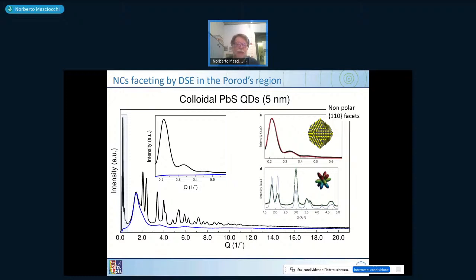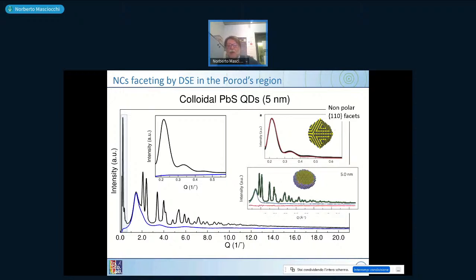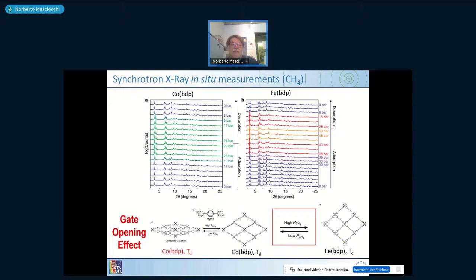So altogether, using the Debye scattering equation in wide angle, the Debye scattering equation in small angle, and the Rietveld refinement at wide angle, you obtain complete information on the morphology of this system. Altogether, of course, it is matched by the fact that you have not only particles with a dense core, but you have an expansion on the surface, which was suitably interpreted by the presence of a core with some defectiveness. The last point I want to discuss again is synchrotron measurement on this kind of